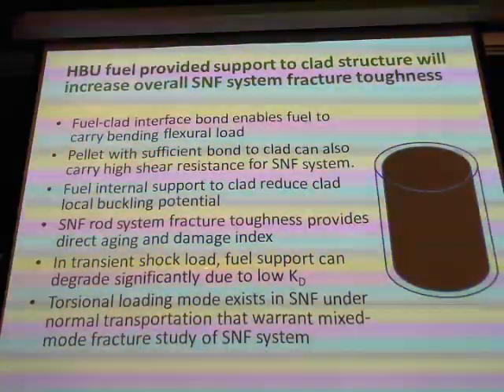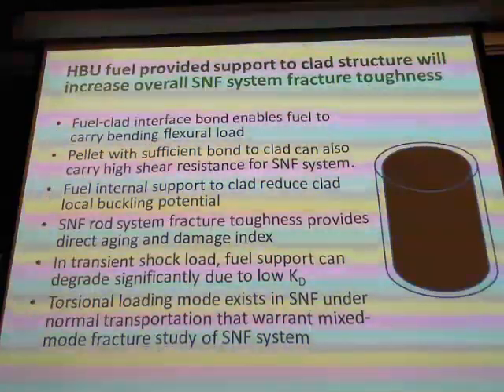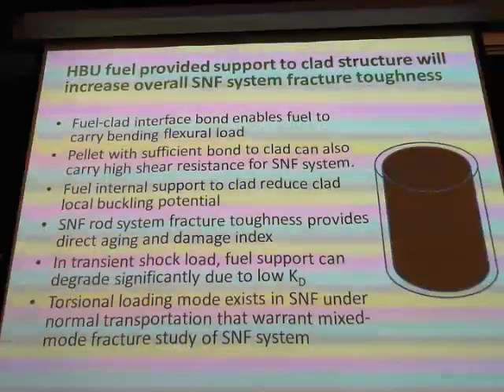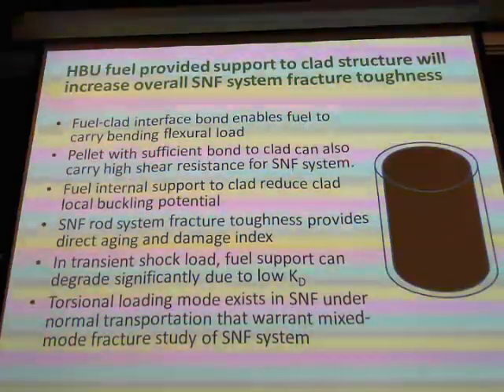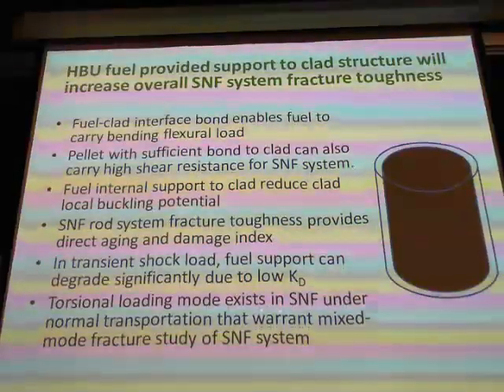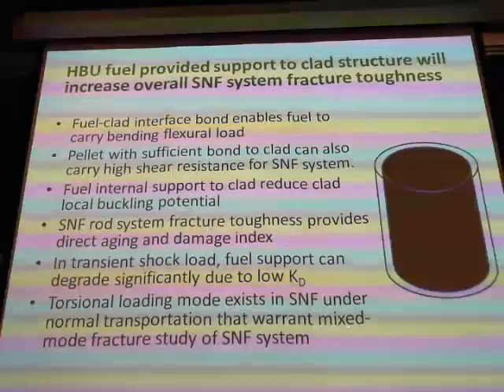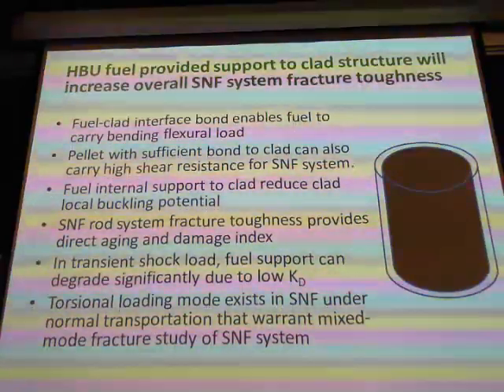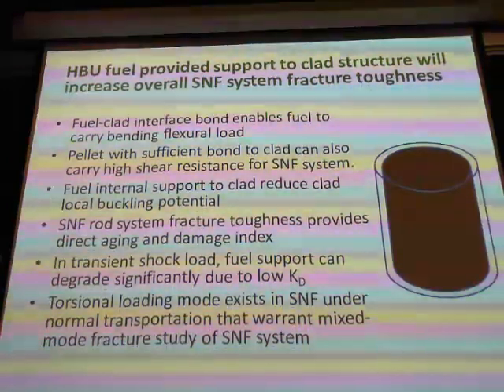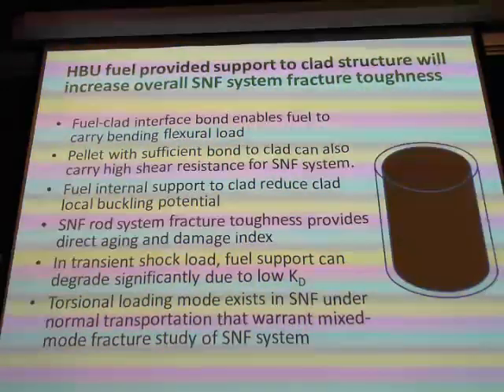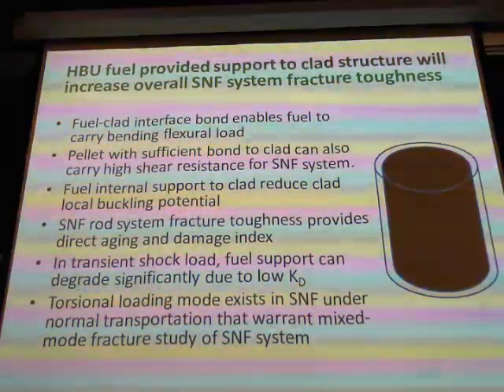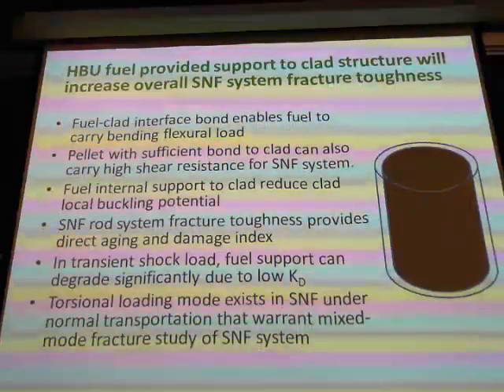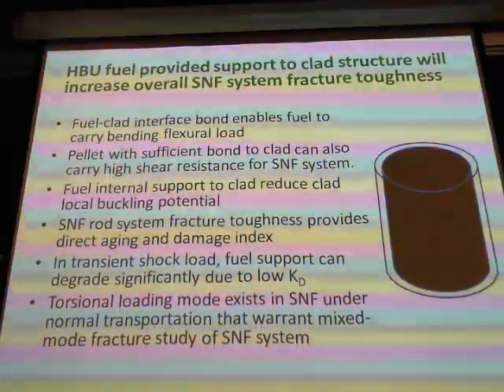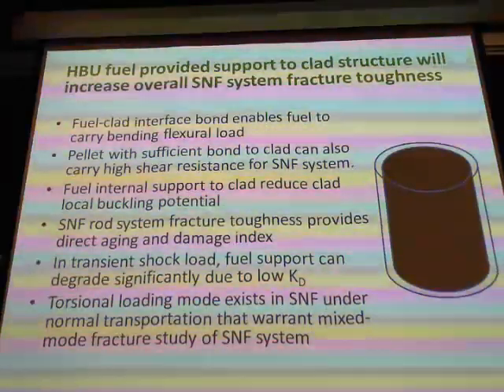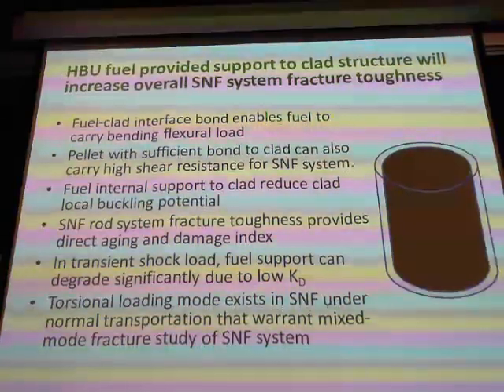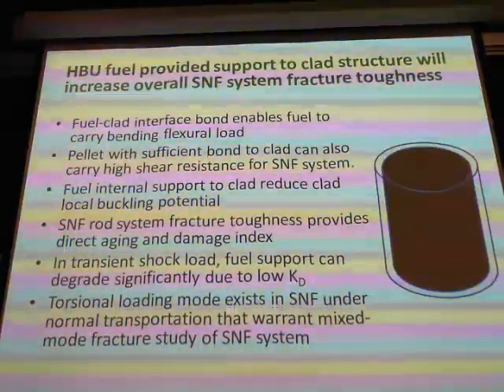And in transient shock, we found that the cumulative damage between transient shock and normal transport conditions is very critical. I have experimented, I will tell you the story there. And torsion loading does exist under normal transport. There's mixed mode, remember mixed mode, you have the torsion and flexure tension. Dr. Gallus from PNNL in 1998 used a very complicated compact tension specimen and very complicated grip. He proved that at a critical angle, mode 1 plus mode 3, the fracture toughness dropped to 50% of mode 1 alone.